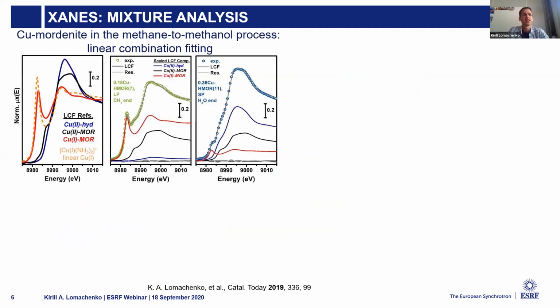So if we can use XANES as a fingerprint, and we know that in our samples there are several equivalent states of a particular atomic species, like copper in the following example, we can in principle, knowing the spectra of the pure components measured beforehand, determine the concentration of these components—the relative weights of these components at each particular moment of time, at each particular step of our reaction, for example.